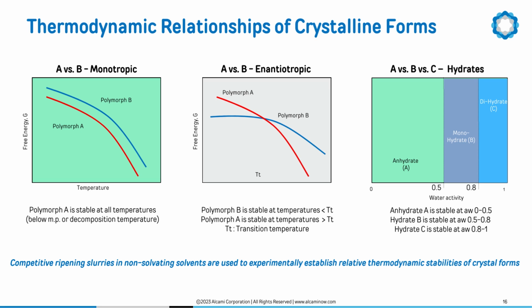For hydrates, the thermodynamic stability at a given temperature is a function of water activity and can be established via ripening of forms in specific aqueous solvent mixtures. From those studies, a phase diagram can be constructed that shows the regions of stability for the anhydrate and the hydrates. Both temperature and water activity dependencies are important and need to be considered at all manufacturing operations, including crystallization, drying, storage, and any secondary process that involves relevant temperatures or aqueous conditions, such as granulation.